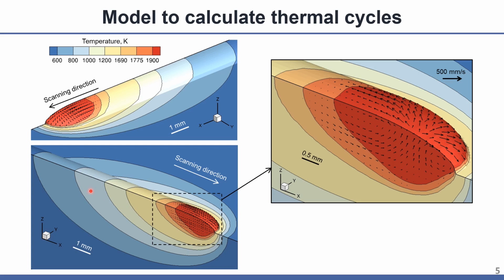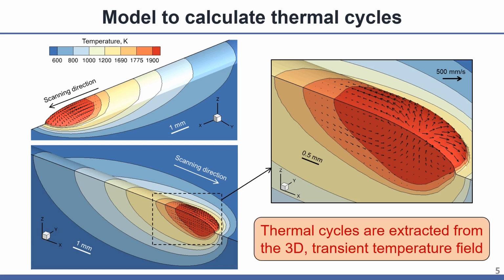The deposit exhibits a curved top surface formed due to the accumulation of powders. The deposit height is maximum at the center of the fusion zone and it decreases with the distance from the center. Black vectors represent the velocity of the flow of the molten material. The flow of liquid metal occurs along the curved top surface of the molten pool from the mid location, where the surface tension is low, to the boundary where the surface tension is high. Thermal cycles were computed from this 3D transient temperature field.